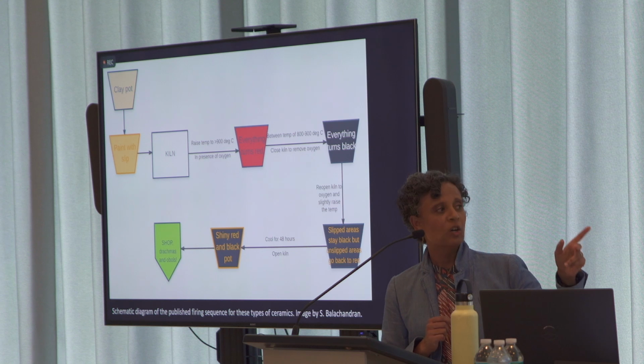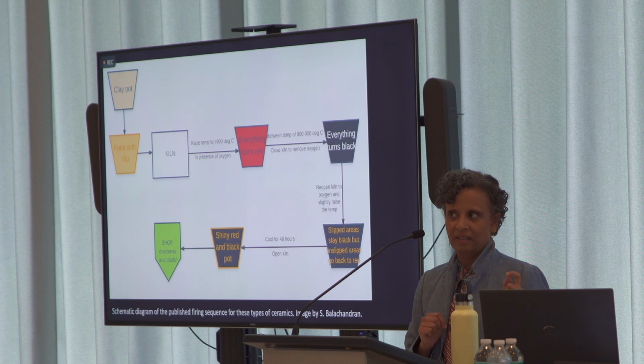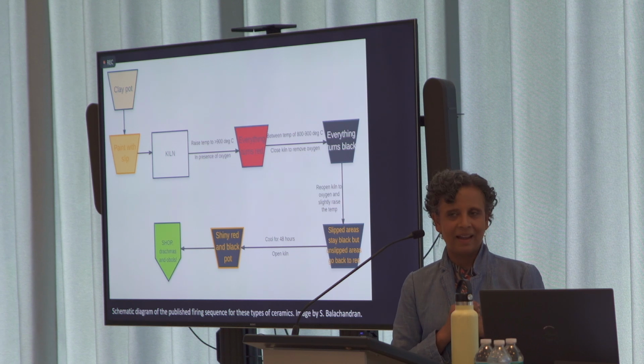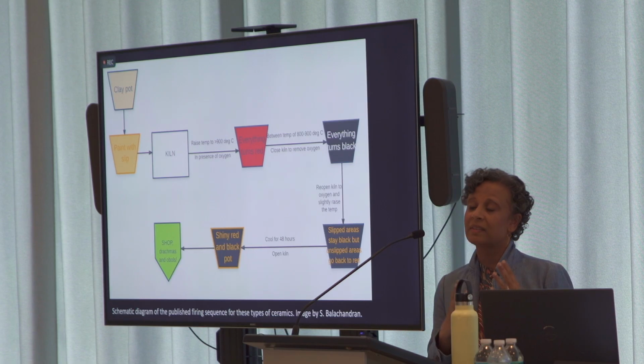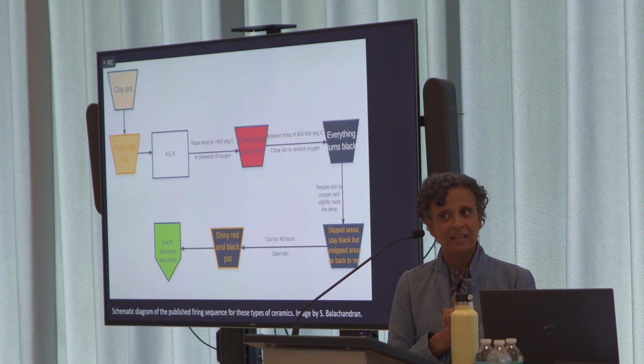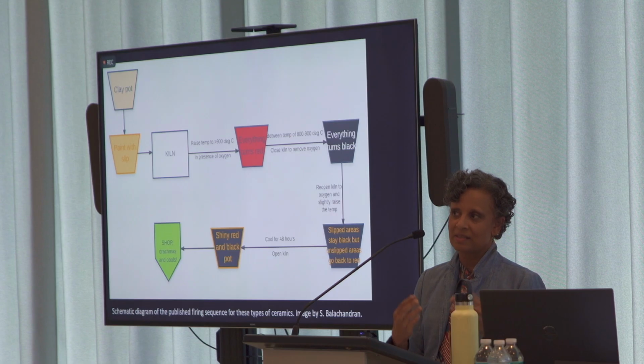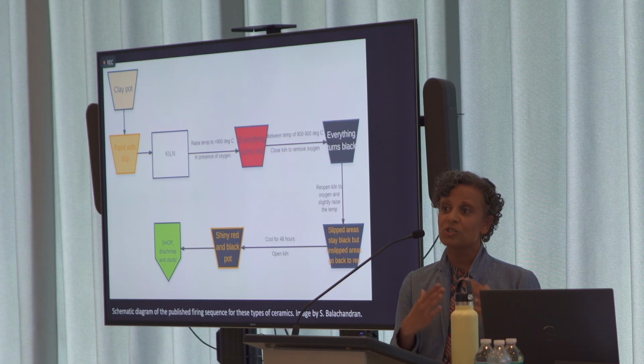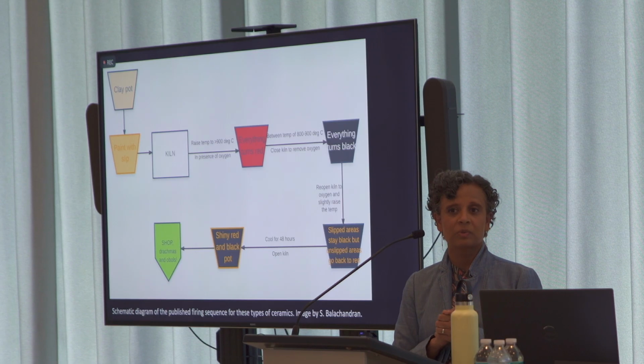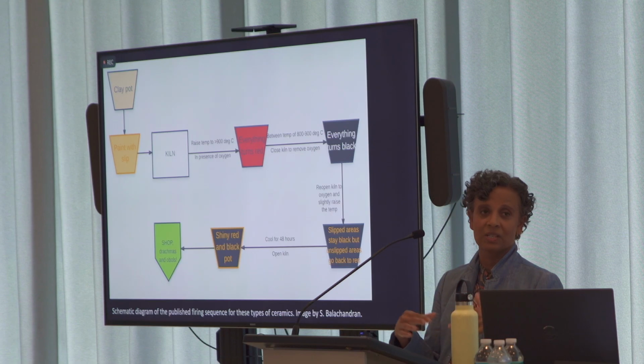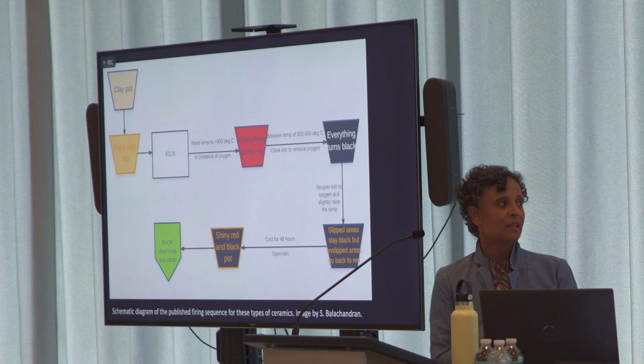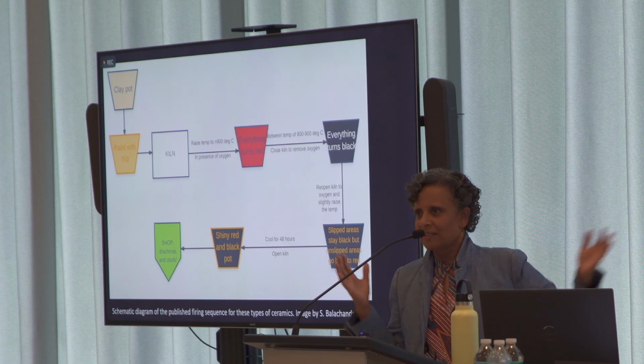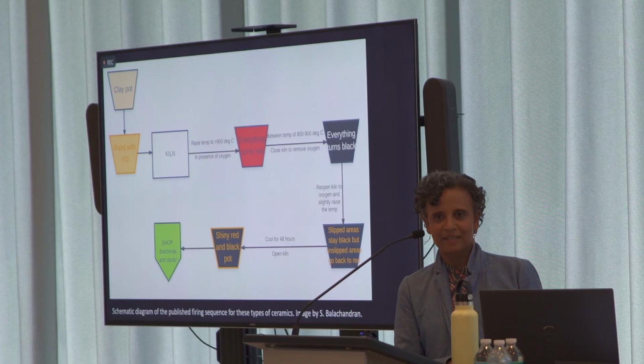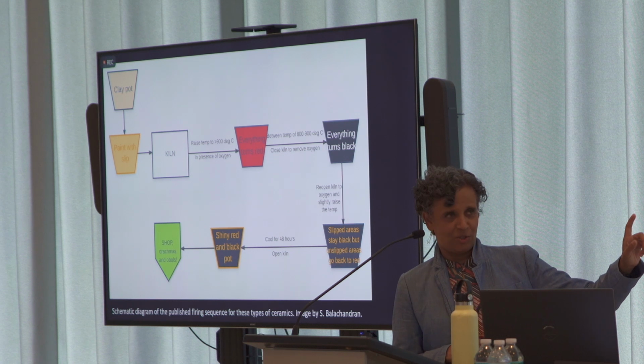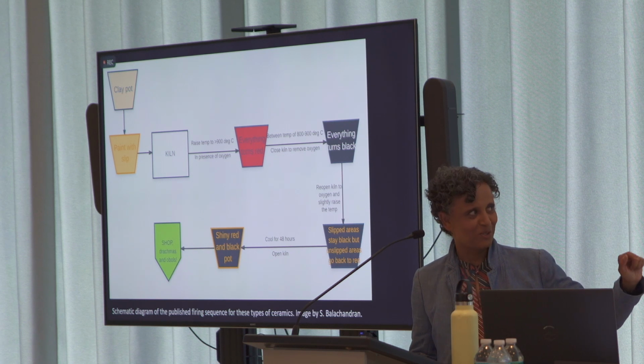Then at some point you reopen the kiln and suddenly only some areas actually turn back to being red. And these are the areas that actually haven't been painted with slip. And that is because there's a very thin layer of glass that should have been created over those areas painted with slip that stops oxygen from diffusing into them and turning them back to red. So then, that's it, you're done. You basically wait until it cools, you open it up, and you've got your perfect pot. This is the simplified version. All right, I have more diagrams if you're interested.